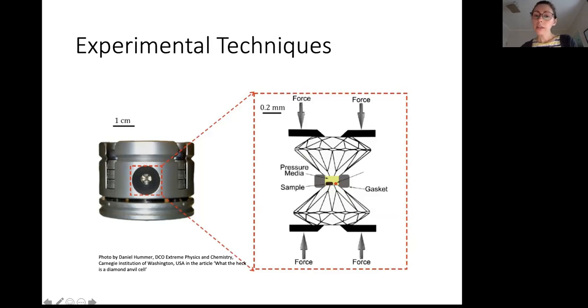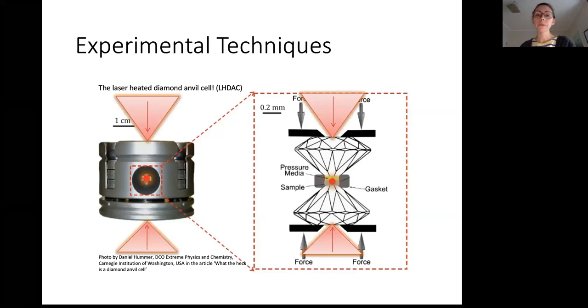Right, so once that's all loaded in the sample chamber between the diamonds, then we compress the cell by closing the two parts, screwing down these diamonds with these screws here, and applying force to the sample. And so just with this little contraption, we can get up to pressures of Earth's lower mantle, and with specialized diamonds you can get much, much higher than that. And so once we have it at pressure, we can put this diamond cell in a focused laser, and that will increase the temperature. So a very finely focused laser right on the sample can bring it up to thousands of degrees, effectively recreating the conditions inside of a planet.